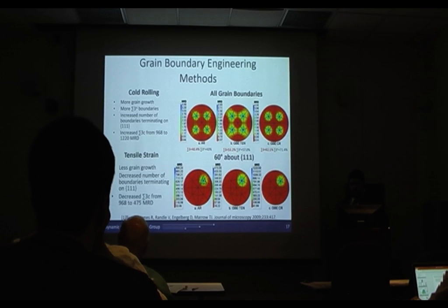But one of the questions is how can we relate this to the bulk corrosion properties? And Dr. Jones and Dr. Randle had suggested a way that we could do this, because they noticed that using two different strain annealing procedures, they actually ended up with somewhat different microstructures. They used a tensile GBE shown in the center and a cold rolled GBE shown on the right.